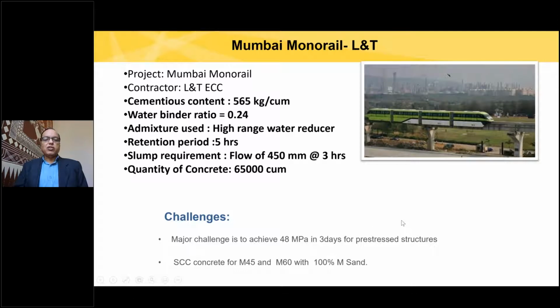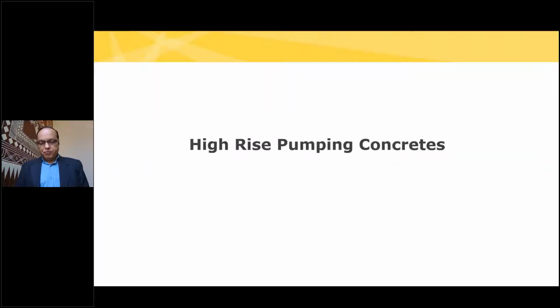The major challenge was to achieve 48 MPa in 3 days for pre-stressing these structures. That was the condition. It was a pre-stressed concrete structure. Therefore, for pre-stressing, you require a certain amount of strength. 48 MPa was that strength. And in this case, we have used 100% M sand. There was no natural sand used. M sand was used 100% in this case.